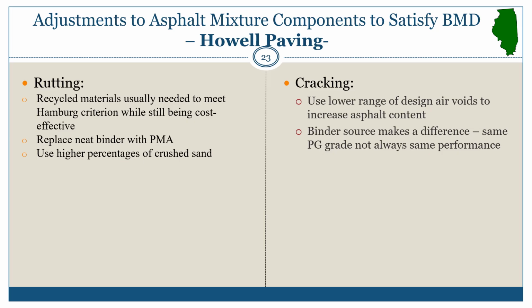If they want to meet cracking, what Pat has found is that they want to lower the range of the design air voids to help increase the asphalt content. Also, binder source makes a big difference. Understand that even though it may have the same PG grade, different sources may result in different levels of performance.